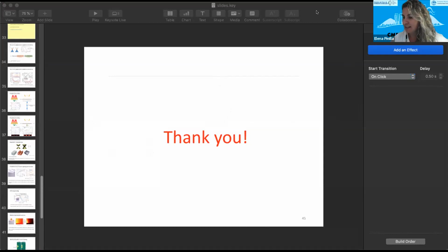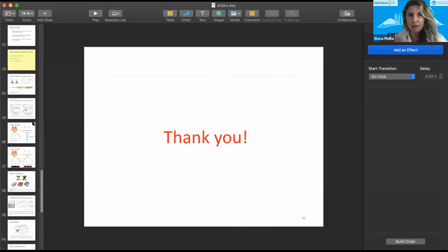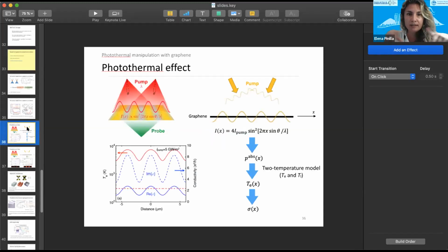I was very interested in the way you can induce this periodicity in the surface of graphene by pumping with two sources, right? So I'm guessing that you can create a pattern, and if you change this pumping, then you can tune the periodicity of the pattern, with basically any type of light? So basically there are two ways of changing the pattern, as you can see here. One way is of course to change the pumping light wavelength, lambda. And the other way is to change the angle of incidence. By doing so, you can change the period of this pattern.